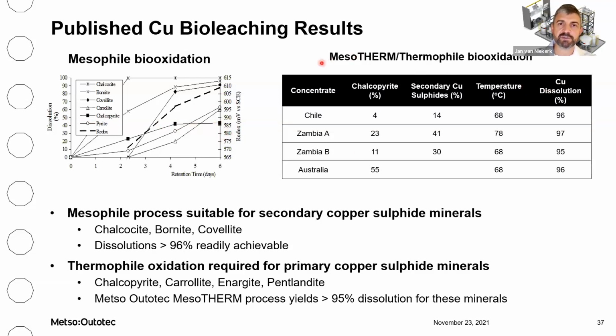However, if we use the mesotherm process, and these are some results from test work that we've done on different concentrate samples with varying mineralogies, you can see at the higher temperatures you can get back to very high copper dissolutions.